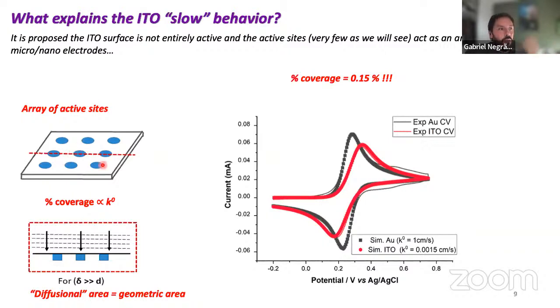So the idea is that we have a lot of islands that are active and parts that are not active. And overall, the behavior that results is an electrode that looks like it has a little bit of this sluggish kinetics. I know that Mauro said that quite a lot because Mauro likes this term. So the overall behavior is sluggish, a slow electrode, even though every single part of those islands behave just like gold. It's as active as any metal. And I think this is a very fair assumption and a very brilliant conclusion to come to, because that's how we can assess, right? We're just looking at the macroscale.